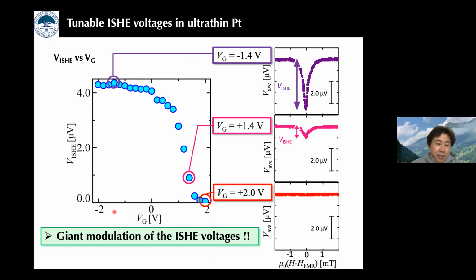So this is the central result of this work: the gate dependence of the inverse spin Hall voltages. As you can see, sizable electromotive forces can be observed at 0 and negative gate voltages. But as we increase the positive gate voltage, the magnitude of the electromotive force monotonically decreases, and finally almost nothing was observed. This is the first experimental demonstration of the giant modulation of the inverse spin Hall effect.